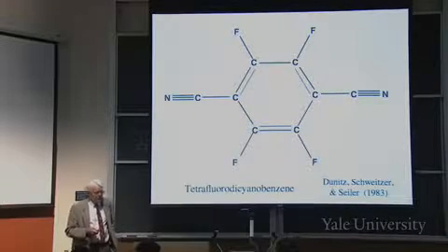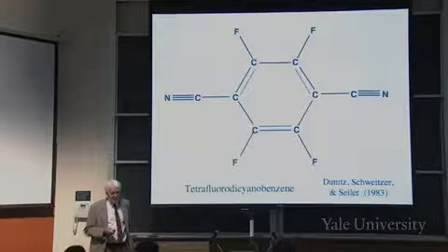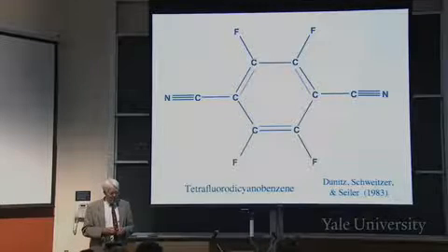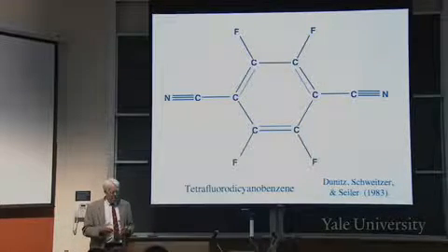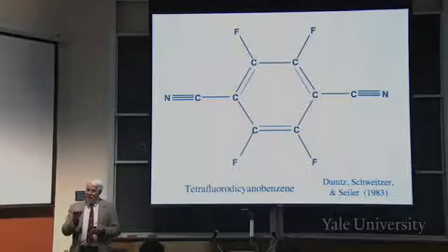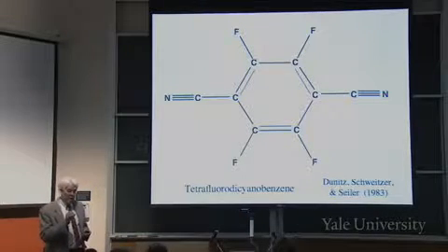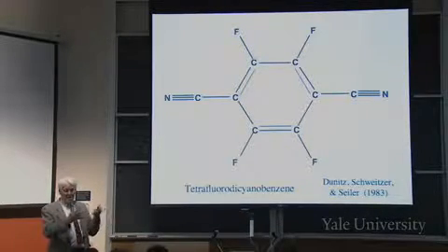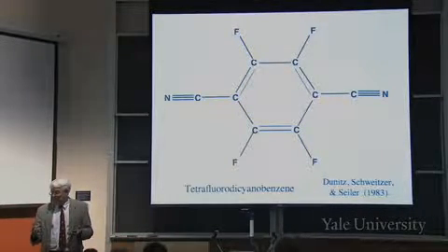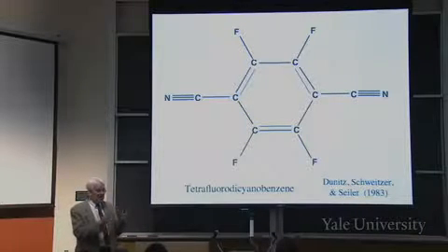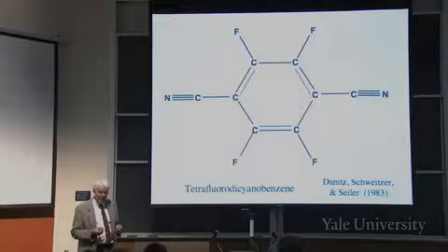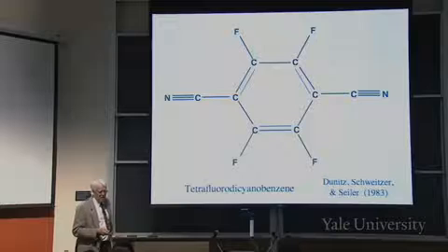Okay. So here's another example done by Dunitz in Switzerland, and these people who were the Seiler and Schweitzer, who were Swiss, who were the progeny of watchmakers and people that do very precise work. Because to do this, you have to have really precise experimental work. If you're going to subtract something from something else and have the difference be meaningful when the numbers are almost precisely the same, right? Remember, we looked at the total electron density. They look just like spheres. So you have to be really good with this if you want to have this be meaningful, and those guys are really good. This was done 25 years ago?